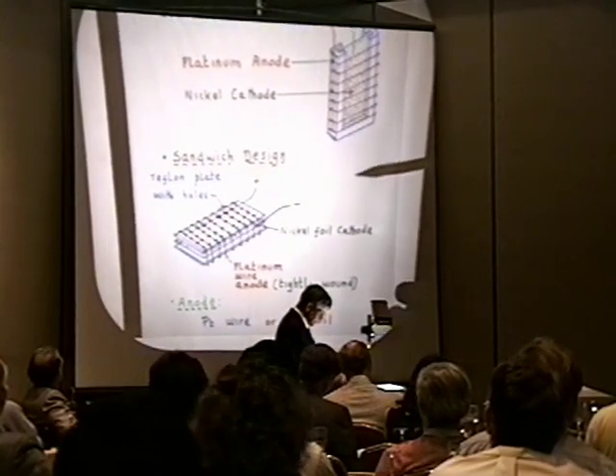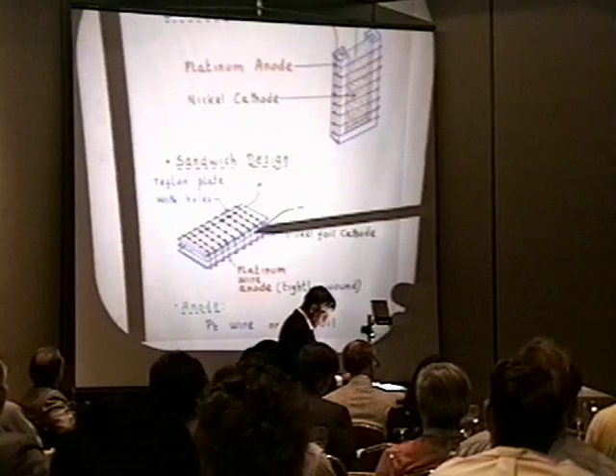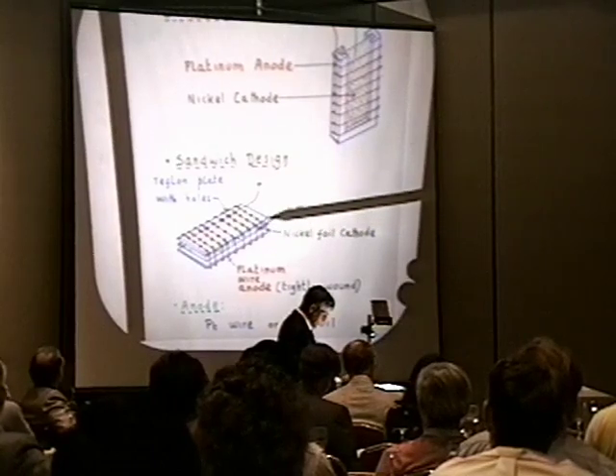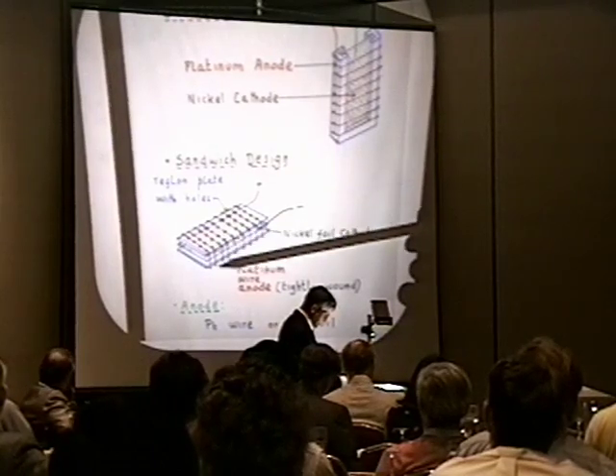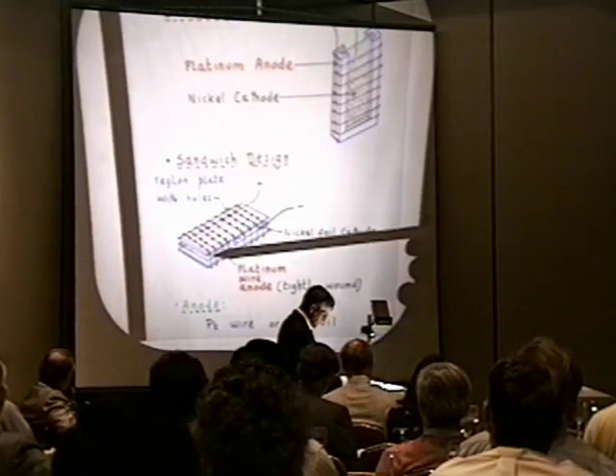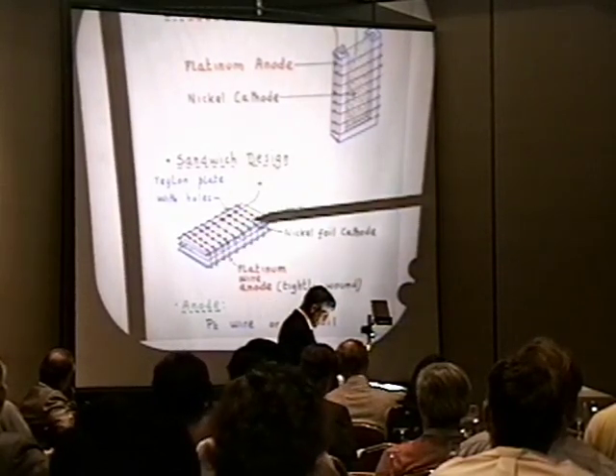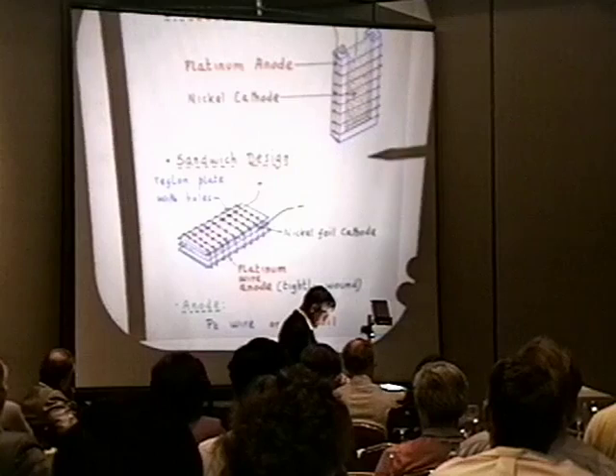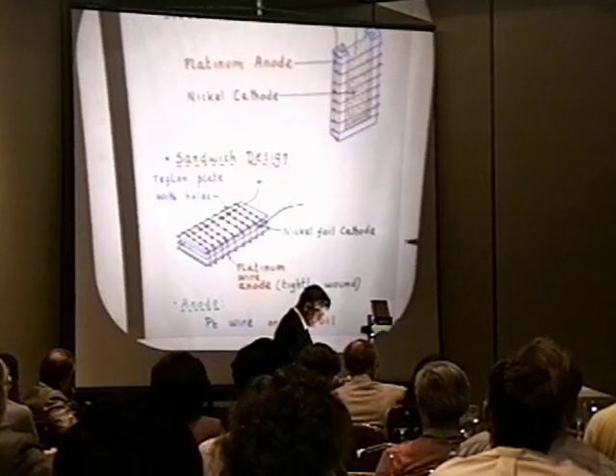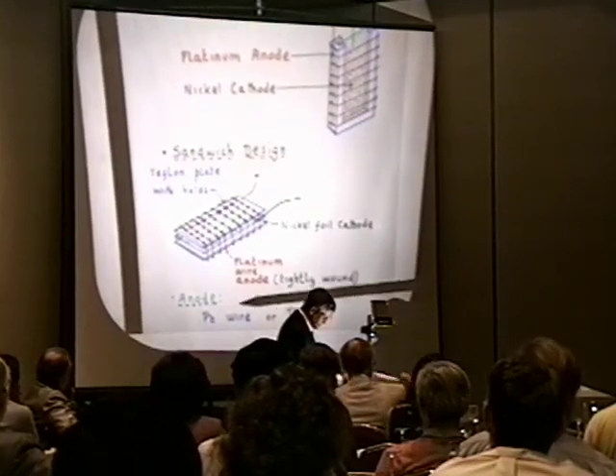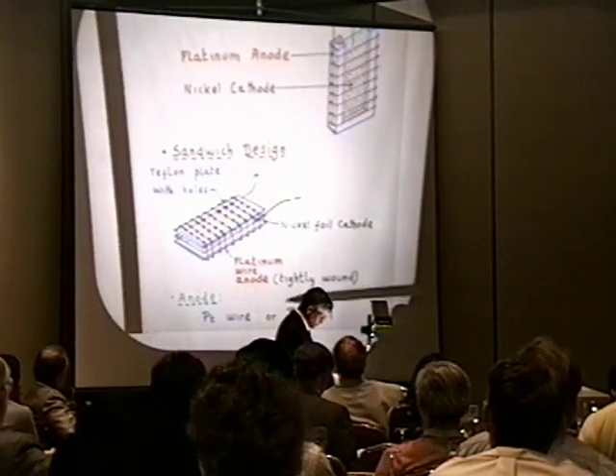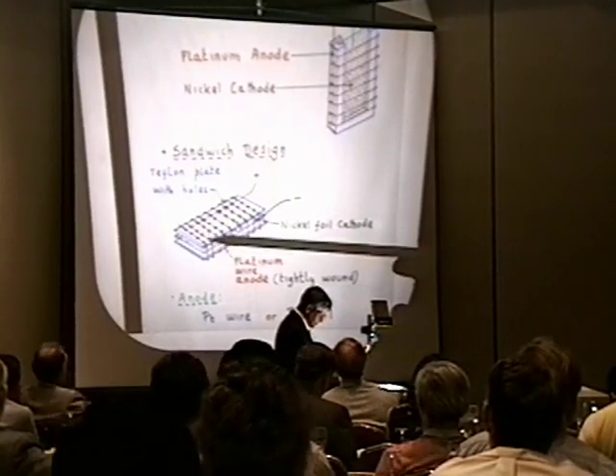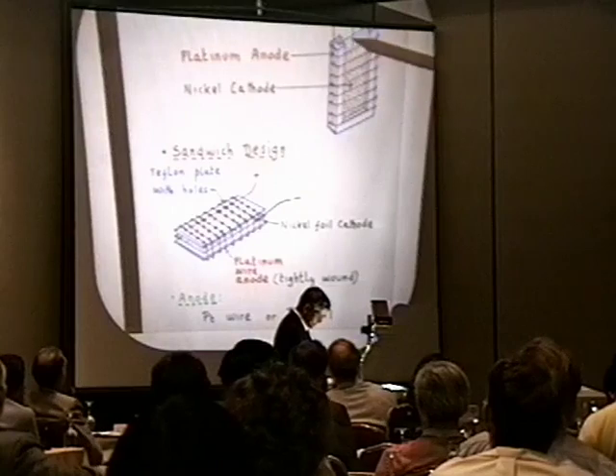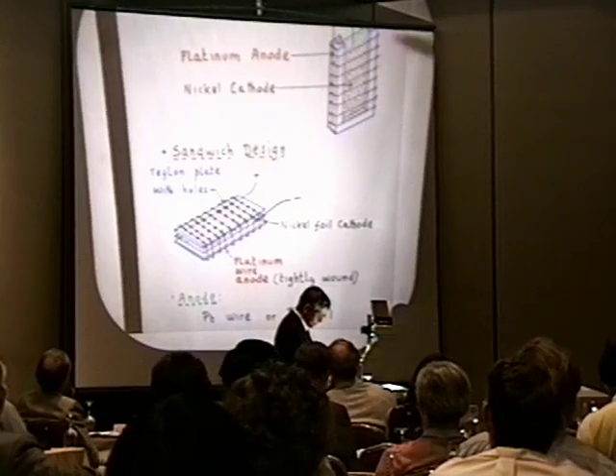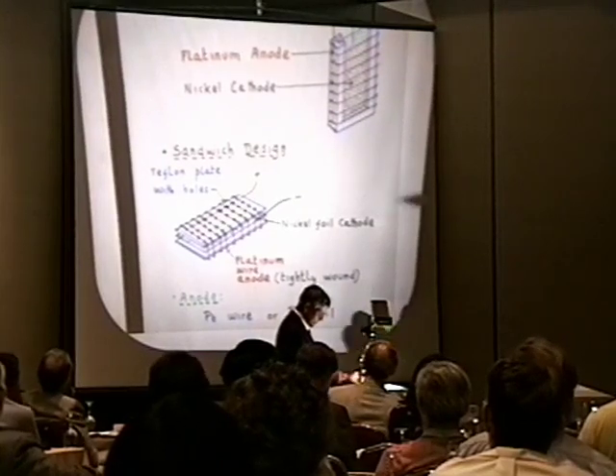In some of the recent experiments, we had another design, what we have called a sandwich design. We have two plates of Teflon with perforations. The nickel is kept in between, and the whole thing is bound together as a package using the platinum wire. A very simple arrangement. Note that in some of our experiments, we have also used platinum foil, so that there will be a 3-layer system, or in this there will be 2 grooves, and there will be a parallel plate, nickel and platinum foil.